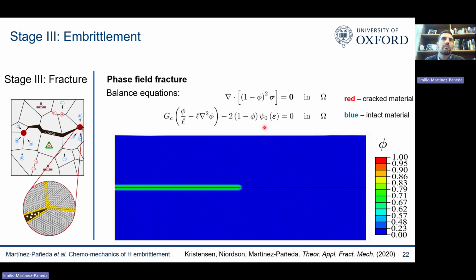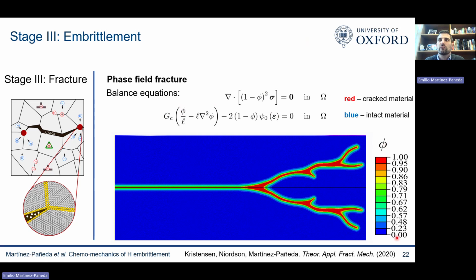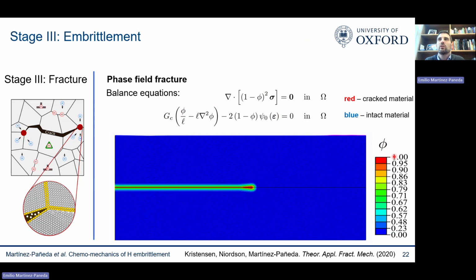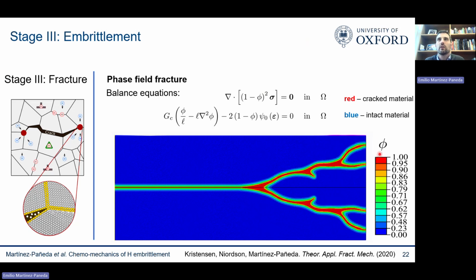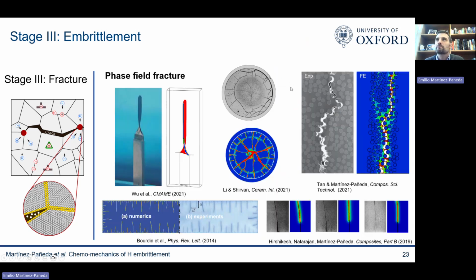It's effectively a competition between the strain energy density, the energy stored in your material, and the fracture toughness - a material property I can easily measure. This is the phase field evolution equation that dictates the value of this phase field, kind of like a damage variable. You see it goes from 0 in intact material points to 1, red, inside of cracks. This is a crack branching due to a dynamic load as predicted by phase field, and like a damage variable, it basically degrades your load carrying capacity.